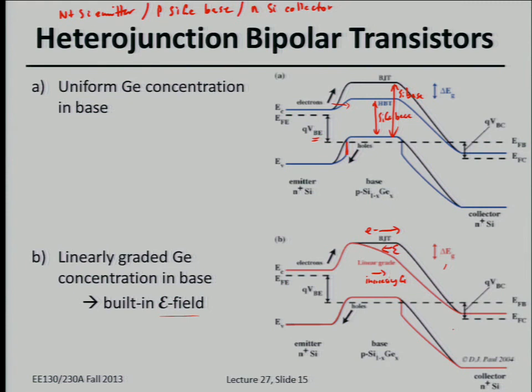It doesn't matter how heavily doped the base is. In this energy band diagram, the conduction band and valence band edges will always stay flat. So the heavy doping, the degenerate doping of the base, doesn't really make a difference. And that is a good point. This base is degenerately doped. Look at this emitter, it's not degenerately doped. So you would normally think, well, that should give you really poor emitter injection efficiency and poor gain. But no, it's not, because you have this Ni squared advantage, right, this ratio.